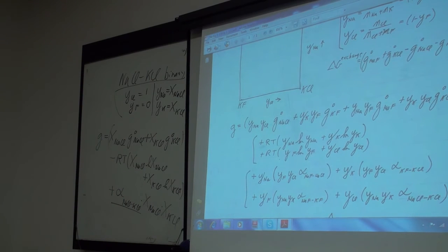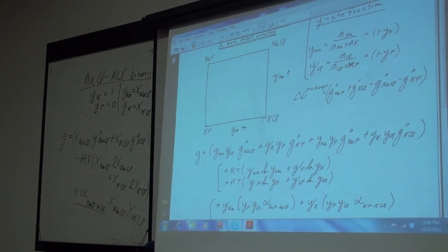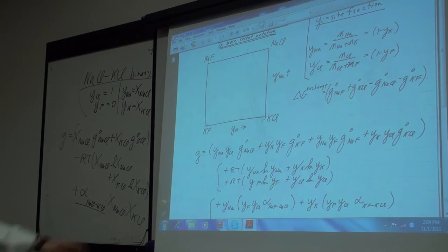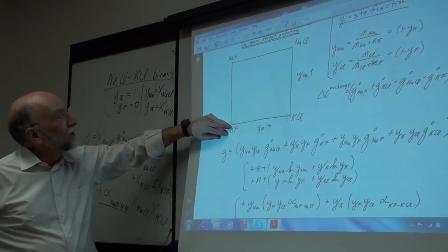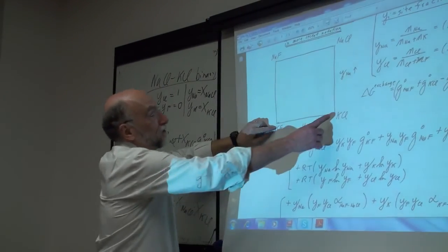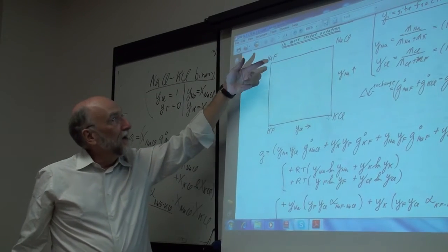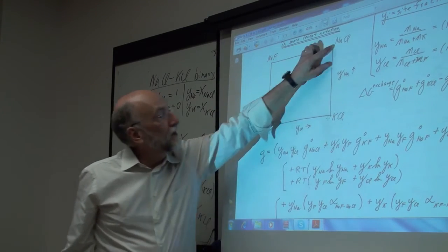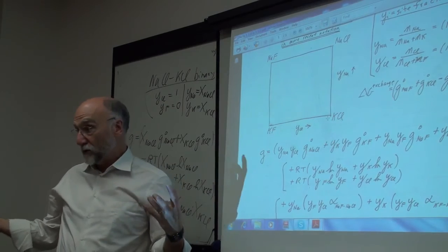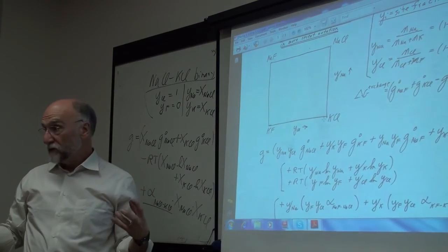And this turns out to actually be the most important thing. And this information, another way of looking at it, is not given by the binary systems. The binary systems only show if I mix sodium fluoride and potassium fluoride, they just show how sodium mixes with potassium. But if I mix any binary system, the first nearest neighbors stay the same. If I mix NaF and KF, all the first nearest neighbors are still fluorine with fluorine. If I mix NaCl and KCl, the first nearest neighbors don't change. Same thing here, if I mix KF and KCl, the first nearest neighbors, anion and cations, don't change.